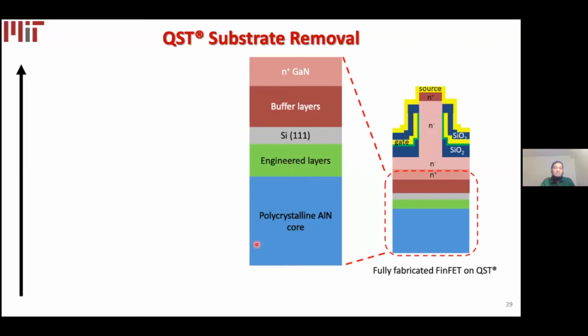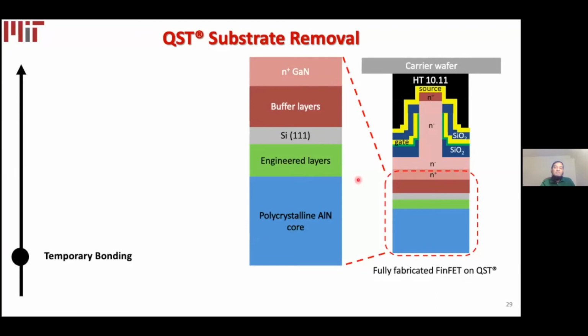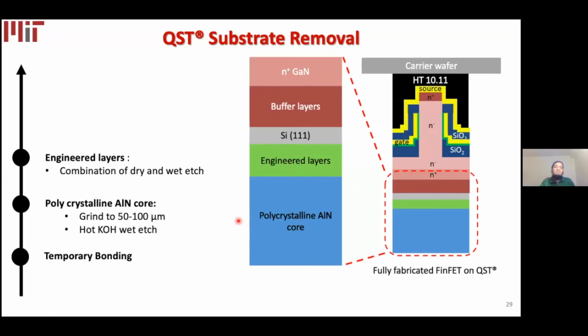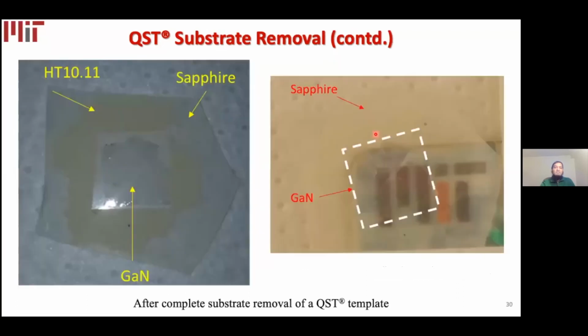So we developed a process where we first use a temporary bonding to attach the sample upside down on a carrier wafer. Then we grind the polycrystalline aluminum nitride from 700 micron to 50 to 100 micron thin, and we use a hot KOH wet etch to remove the rest of the aluminum nitride. Then we use a combination of dry and wet etch to remove the engineered layers. And we dry etch the silicon 111 and also time dry etch the GaN buffer layer to stop on the N+ drain.